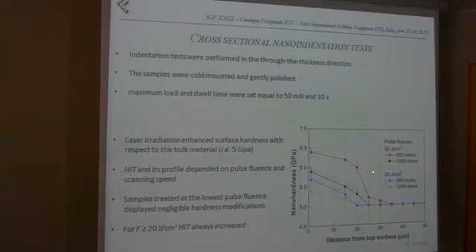So here I reported just a few of the tests that we performed, but of course we performed the tests for the whole matrix, and we verified once again that for the lower level of pulse fluence we didn't have a huge variation of hardness. It was more or less comparable with the as received. While for the other tests we had a harder surface that was going gradually to meet the hardness of the baseline material, so of the as received.